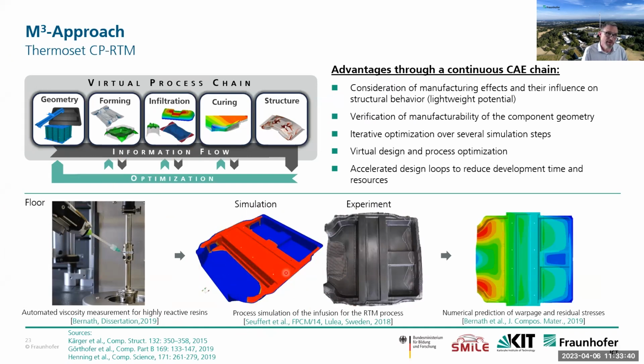A lot of this work is coordinated and done by my colleague Professor Kerger, who together with me is running the research institute at FAST for lightweighting. And we are also working with our material characterization folks. You see this plate rheometer is a special development because these highly reactive resins have to be mixed and injected immediately, because when you do it in a conventional way, it's already cured before you start measuring. So we have to adapt methods to get real data for what's happening in the process during the manufacturing, which is a couple of seconds only.